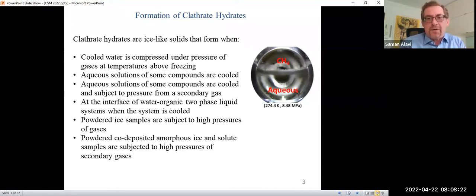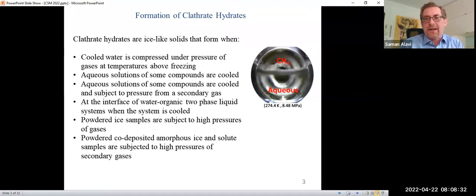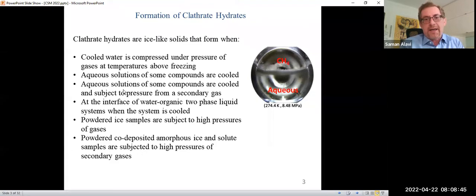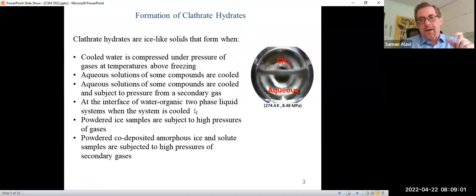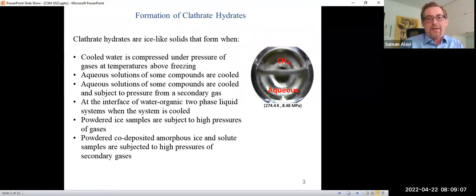Another way, for liquid guests which are larger — if they're miscible with water — is to just form the solution, such as THF with water, and just cool it. We'll see that above the freezing temperature of the water, a solid clathrate hydrate forms with, for example, THF. For some other guests, in addition to cooling the water phase, we may need to subject the solution to a pressure of a secondary gas for them to form. In some cases, we can have a water-organic two-phase system and cool it, and at the interface we see clathrate hydrates forming — that's the case for cyclopentane.